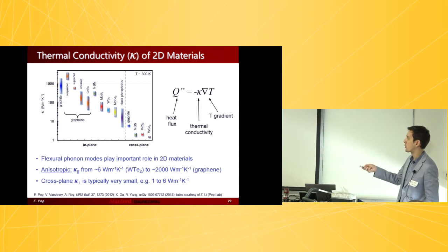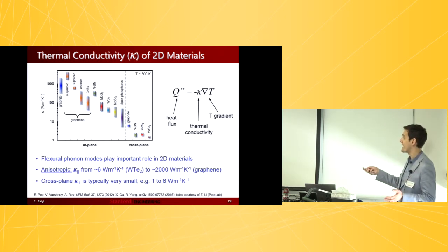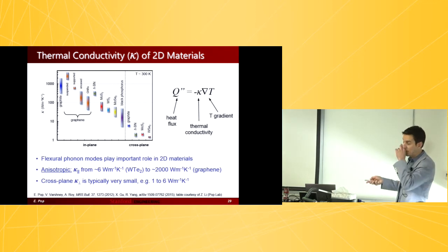This is a huge, huge range for thermal properties. Thermal properties do not vary like electrical properties. You can only really vary them in solids by 3 or 4 orders of magnitude. This is it for pretty much all solids, right? Maybe you can go another order of magnitude lower in really, really disordered things or plastics.